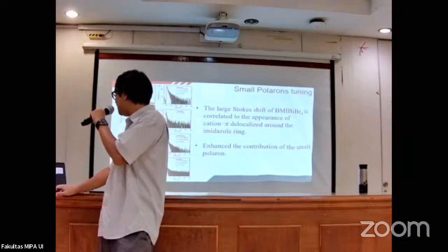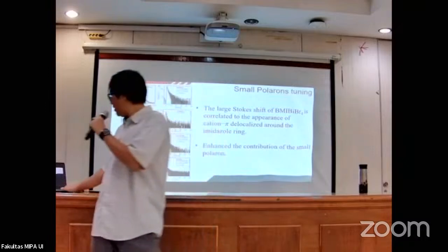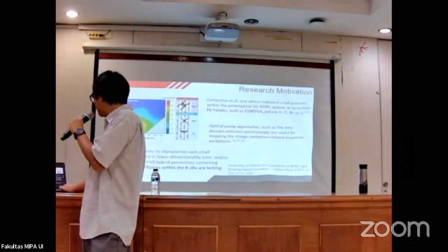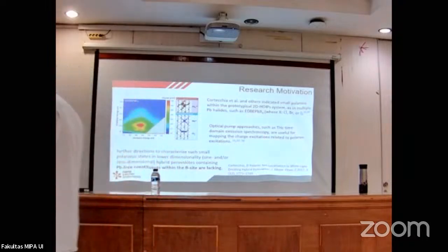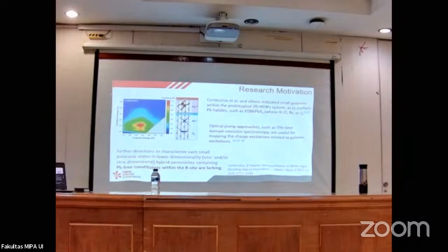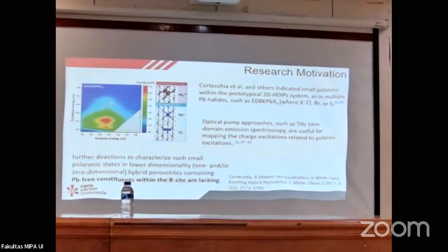Okay, so we come with a new concept here, because I need to mention a bit back to the paper of Cortecchia. In the work of Cortecchia, he used this 2D map where we can plot the information that the emission energy is spread as a small contour within this regime. For those not so familiar with polarons, in the 2D case, polarons can be generated when we have a coexistence of what we call a self-trapped electron and hole simultaneously. These two ingredients have already been published by so many groups.